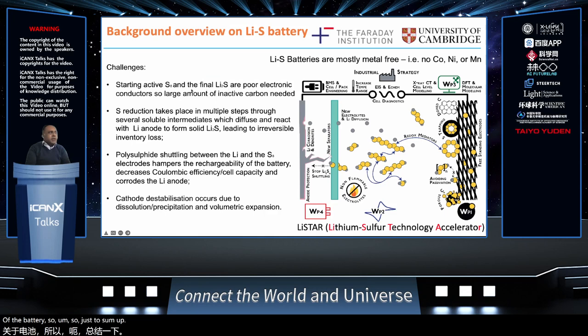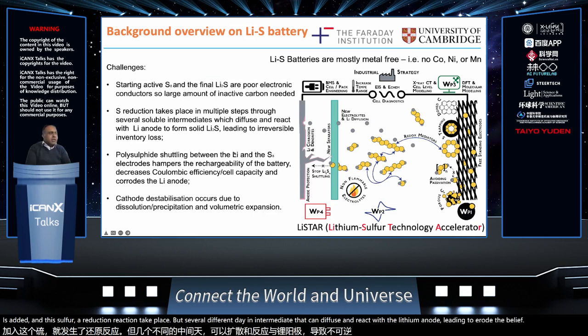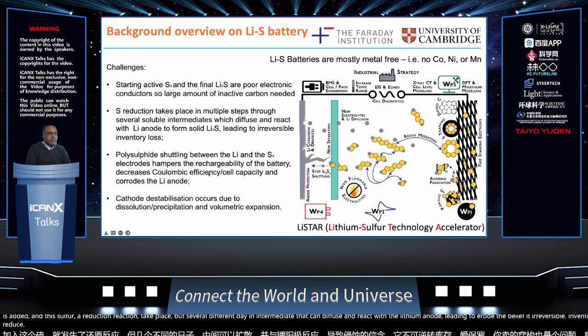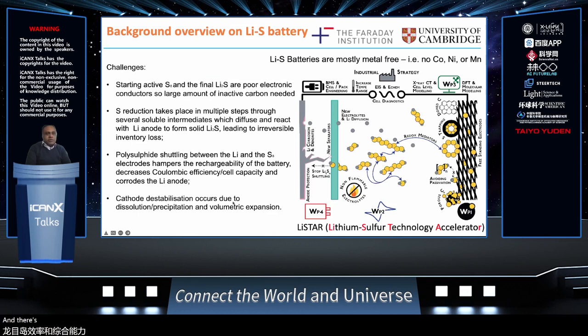So just to sum up, the starting active material is S8. The final products that we end up with in the lithium sulfur batteries, Li2S, both of these are electrically insulating. And so to mitigate for this, there's a large amount of inactive carbon that is added. And this sulfur reduction reaction takes place by several different intermediates that can diffuse and react with the lithium anode, leading to irreversible inventory loss. Polysulfide shuttling is also a problem, which can reduce coulombic efficiency and overall capacity. There's also challenges with expansion of the electrodes that must be overcome.